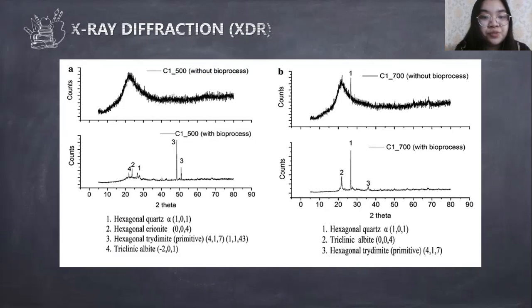With the result, it supported the idea of using earthworm for a biomineralization mechanism, as it can contribute to the atomic arrangement and modify the original structure into a crystalline structure. For B, it also used the rice husk, but at 700 degrees Celsius. For not using bioprocess, there is the amorphous structure and only one diffraction plane with low quartz can be seen.